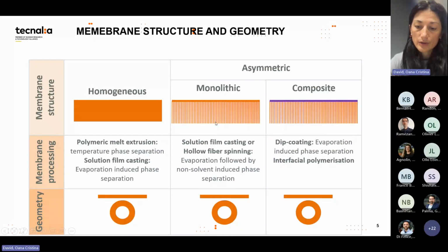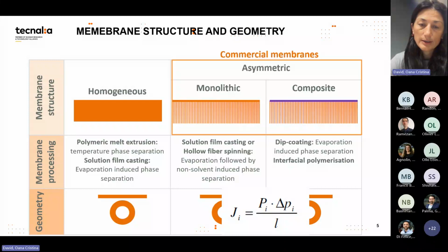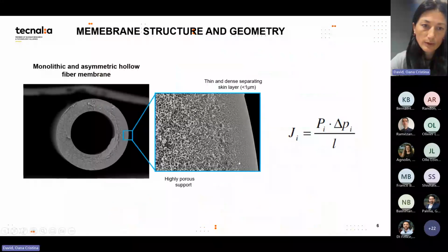When we make an asymmetric structure, we make it because we want the dense part, the one that actually does the separation, to be as thin as possible. So we need to have, as Helen showed before, this very thin layer and a porous support. We can make a monolithic structure, which means that we make both parts at the same time from the same material, the same polymer, or we can make a composite structure as was shown before by Heron. I will not go into details on that, but I will go into details on hollow fiber spinning, and this is what we are doing at Tecnalia.